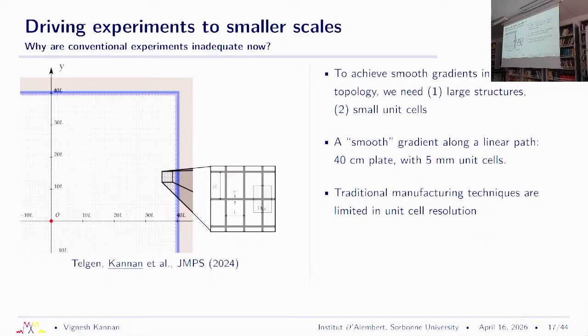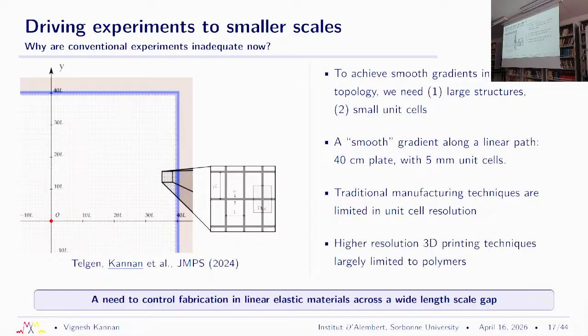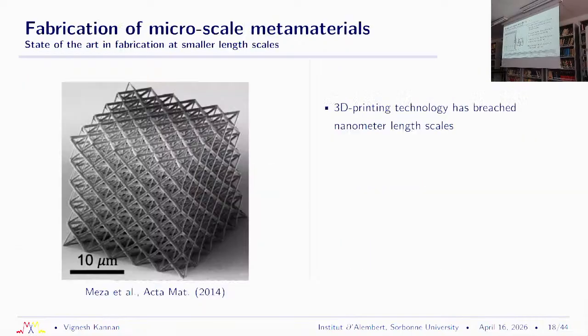No, there's no matrix. It's basically beams and holes inside. So we needed to come up with higher resolution manufacturing techniques, and a lot of these 3D printing techniques we discovered were largely limited to polymers, where you have viscoelastic damping of the material. So we needed to decouple the material dissipation from the structural dispersion of the wave through the material, and that's when we started chancing upon different types of microfabrication techniques.